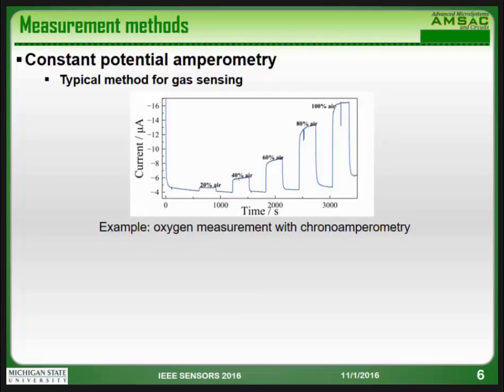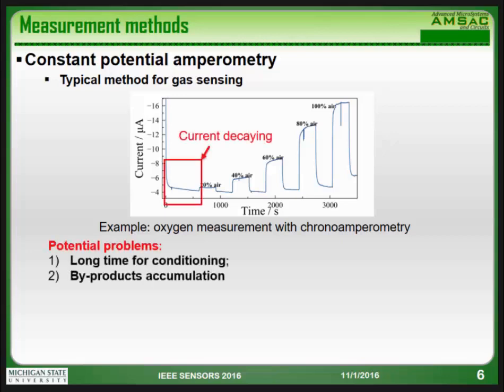So we have the sensor. Now we want to measure it. Generally, the method for gas sensing is constant potential amperometry, which means we apply a constant potential on the working electrode, then we record the current, and then we do the final analysis. Here shows an example; we use it for oxygen sensing. The potential problem is that in this period, the sensor needs to decay, which means the charging current needs to decay to a very stable stage before we do the next measurement. So this phase will take a very long time.